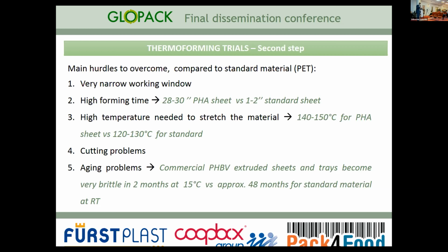Also, we had some cutting problems because the material was brittle. Cutting problems means that after you thermoform the trays, you have to cut them to have a good edge, so that afterwards it's possible to use them in the sealing machine. Since the material is a little too brittle in the cutting, you can have some small particles detaching, and the edge is not so nice. And this is a problem also during the sealing process, because they are trays for food, so they must not release particles and things like that.